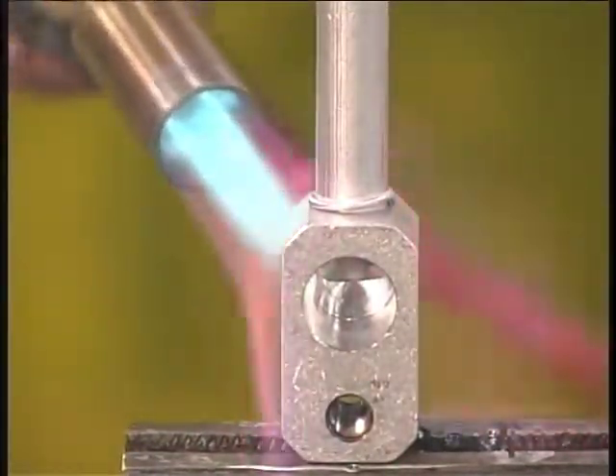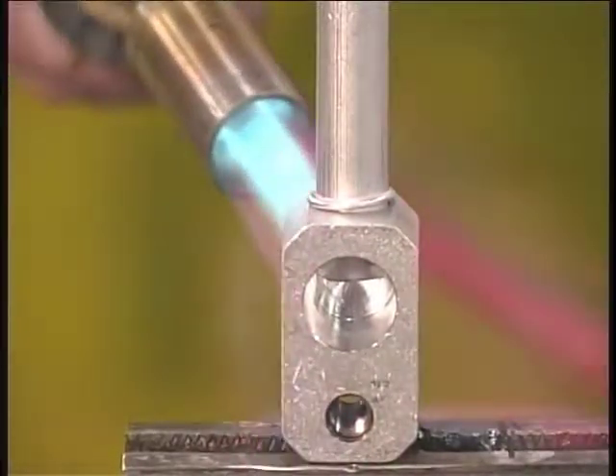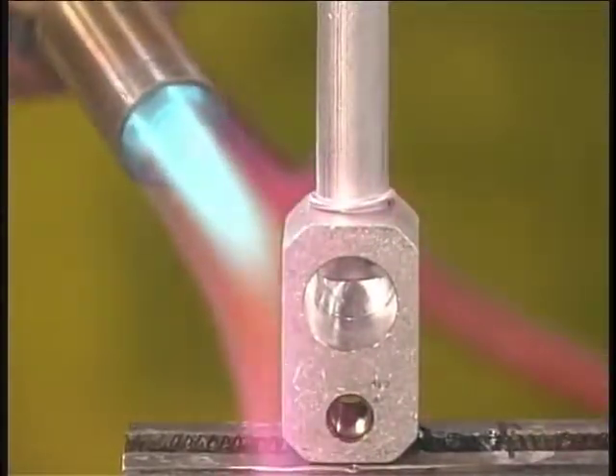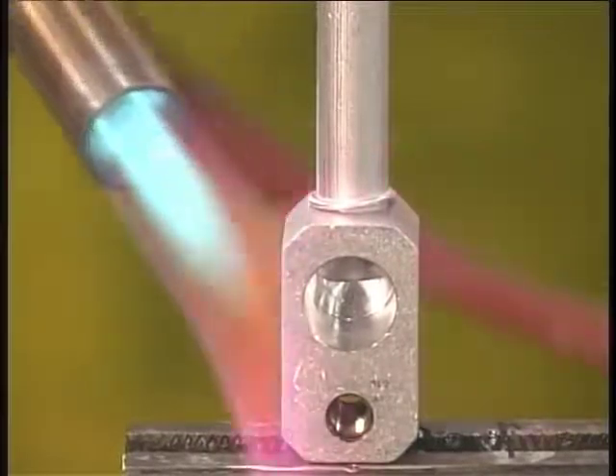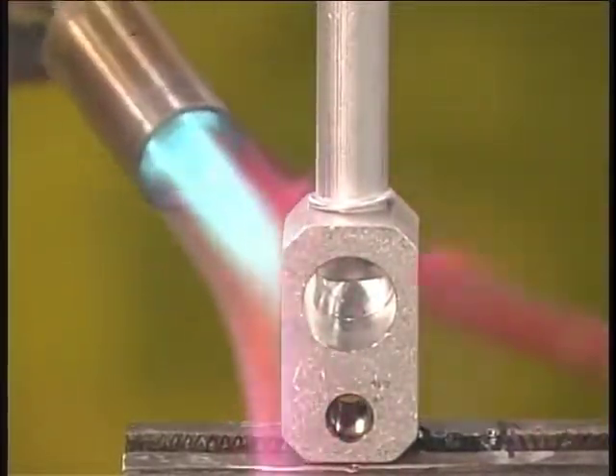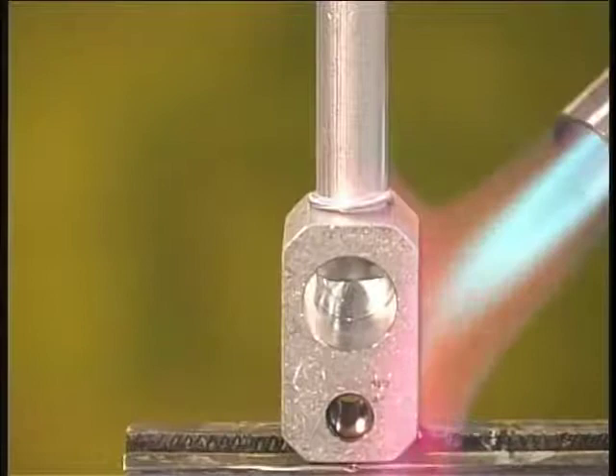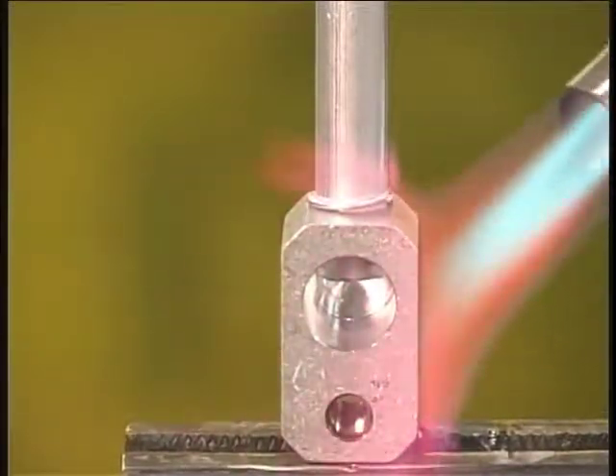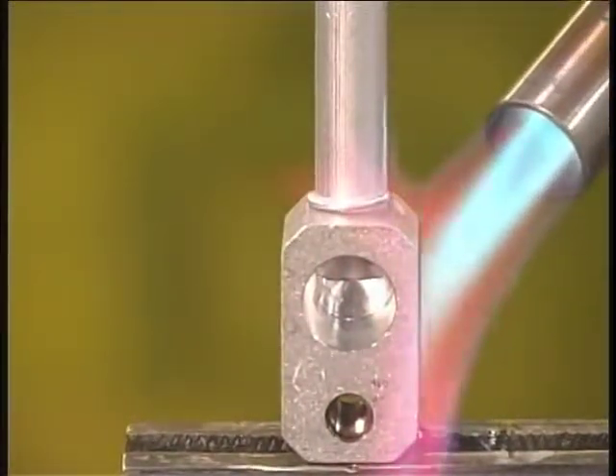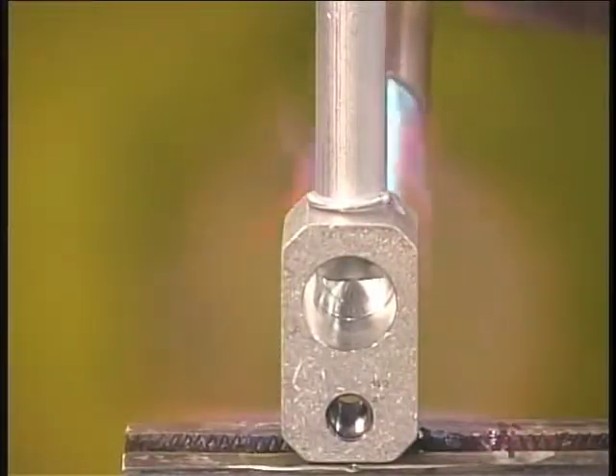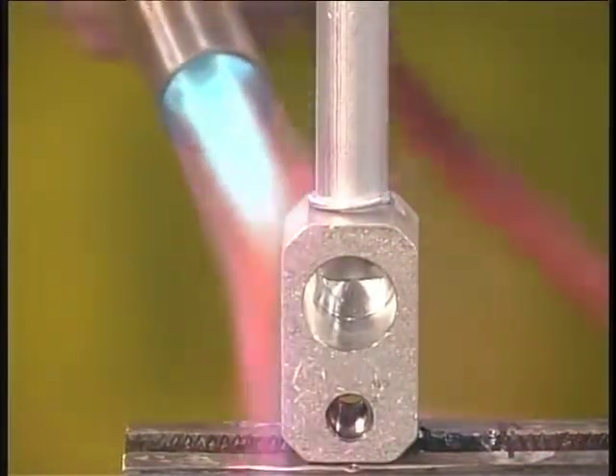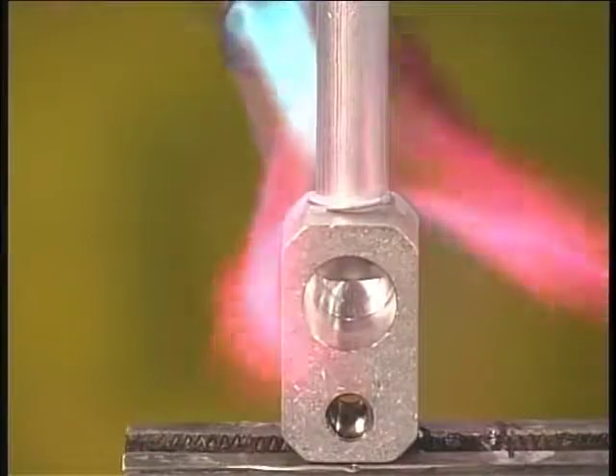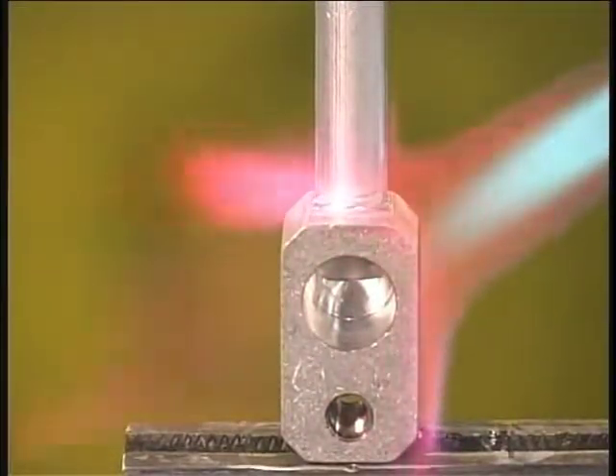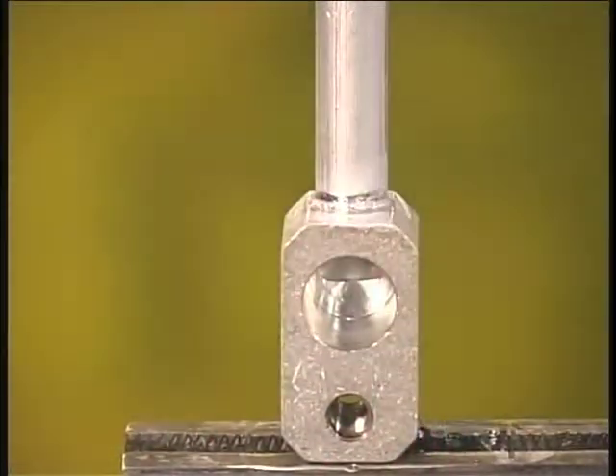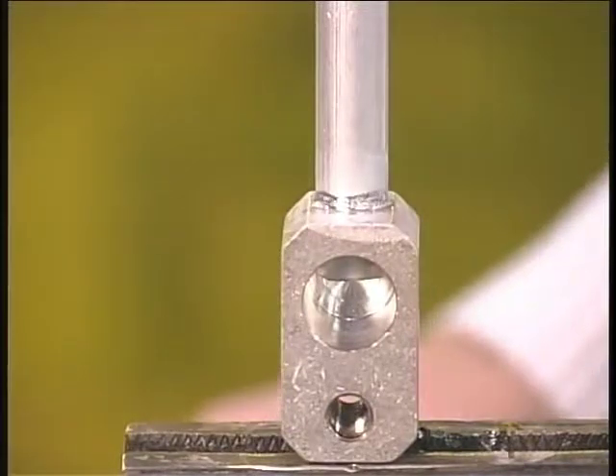It is important to keep the torch moving to prevent blistering the surface of the block. Notice the tip of the blue flame cone is just touching the surface being heated. As heat continues to be applied to the block, the tube and the braze ring heat up also. As the components near the correct temperature, the surface of the braze ring will change appearance and become dull. At this point, the torch is moved upwards slightly. At that very instant, the braze ring will break down and the liquid flux will cause the molten filler metal to flow into the joint.